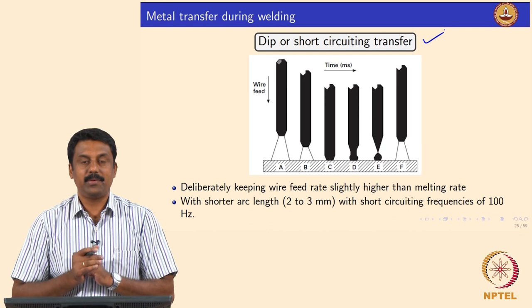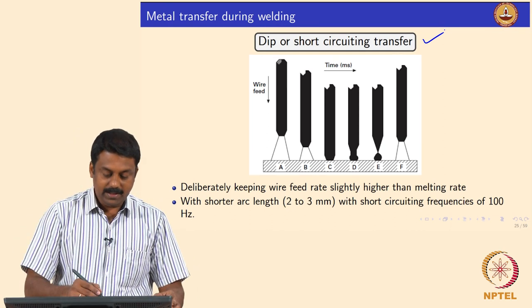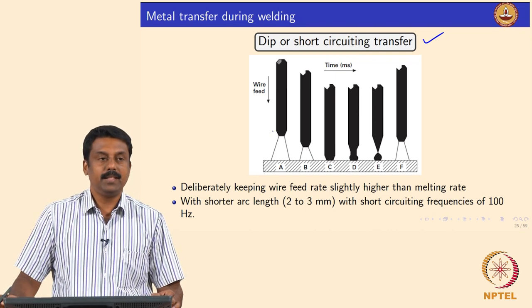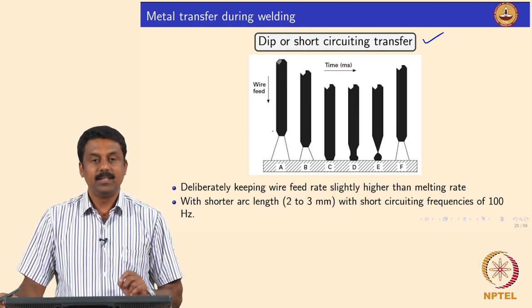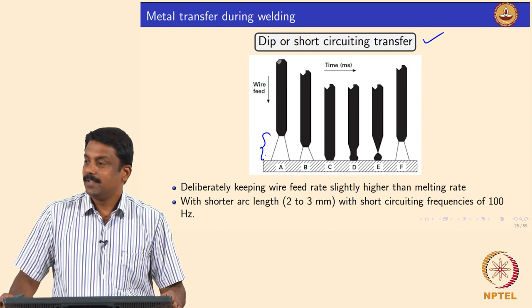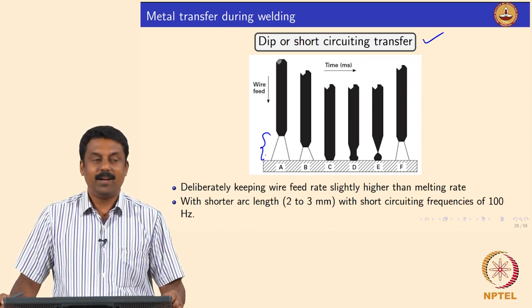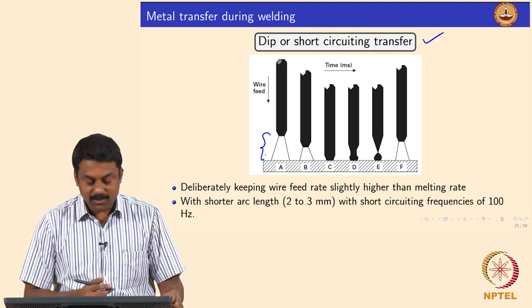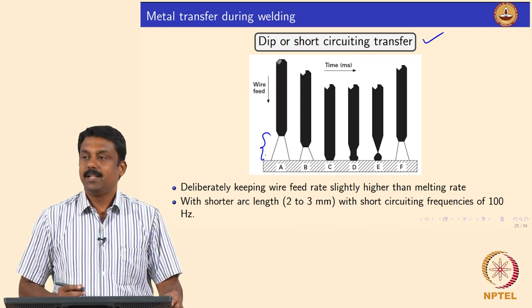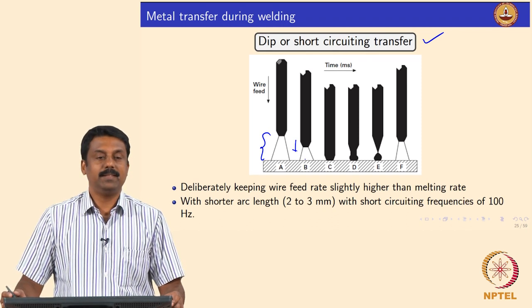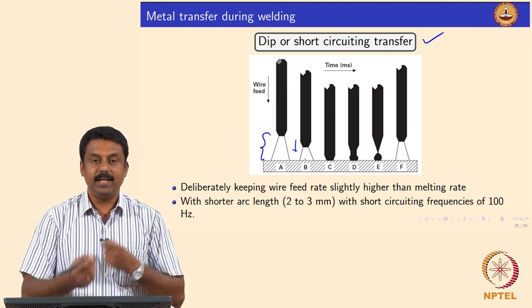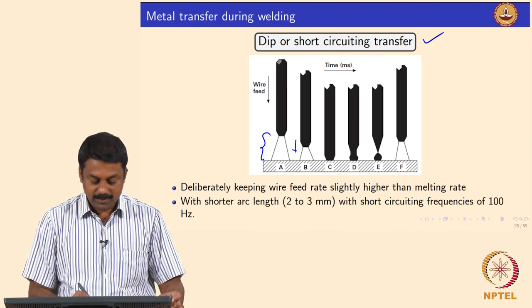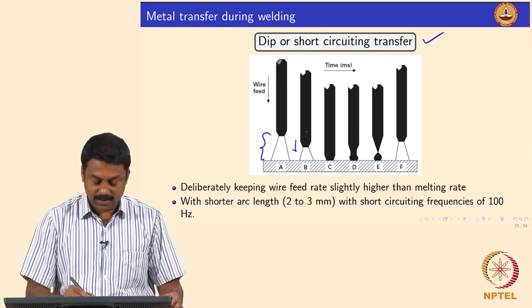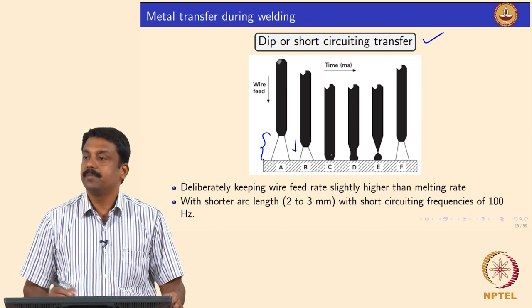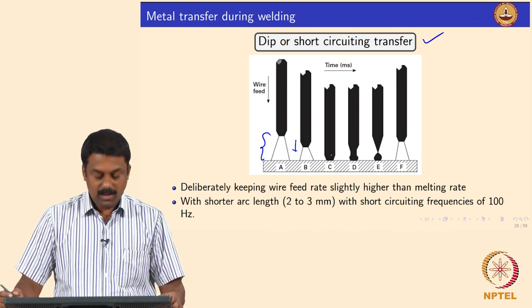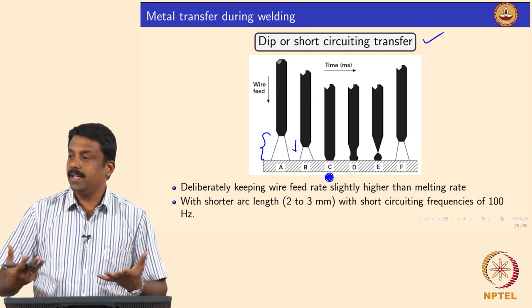One example schematic I show you here is from Prof. John Norrish's book. Basically, the wire is continuously fed, is it not? If the melting rate is equal to the wire feed rate, what happens to the arc length? If the melting rate is equal to the wire feed rate, the arc length becomes constant. But you can also carefully manipulate the feeding rate in such a way that you slowly bring the wire towards the workpiece or weld pool. So, increase the speed of wire feeding such that you slowly bring the filler to the workpiece and establish a short circuiting, right. It is clear. And once the short circuiting happens, you also increase the current.